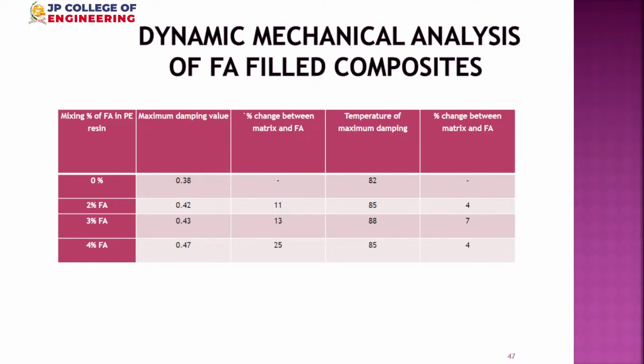So the results indicate that as you increase the amount of fly ash content, the maximum damping value goes 0.38, 0.42, 0.43, and 0.47, and so on. So this shows that the damping value is increasing as you increase the fly ash, nearing around 0.5. That is a good value for good damping behavior. So the fly ash additions improve the thermal stability and also improve the damping capacity. That's our final finding. Next slide, please.